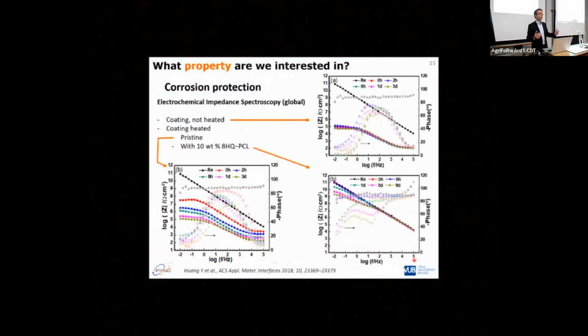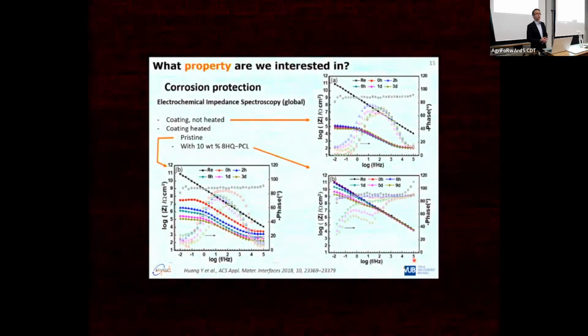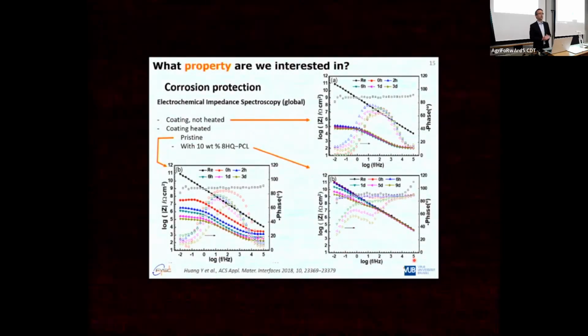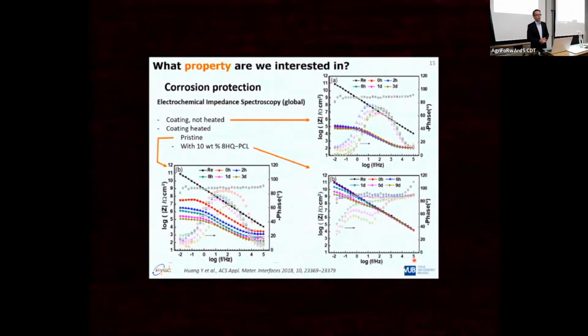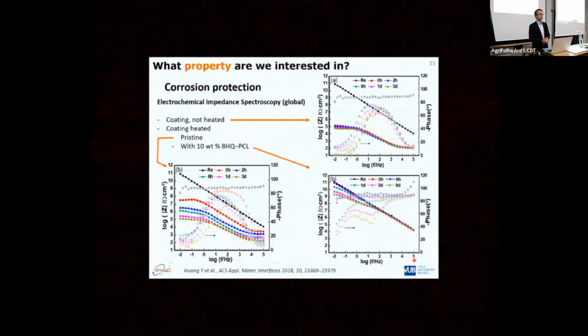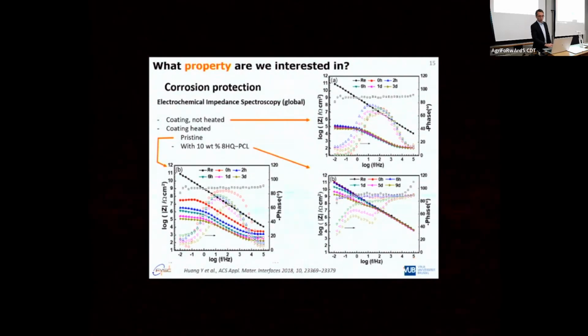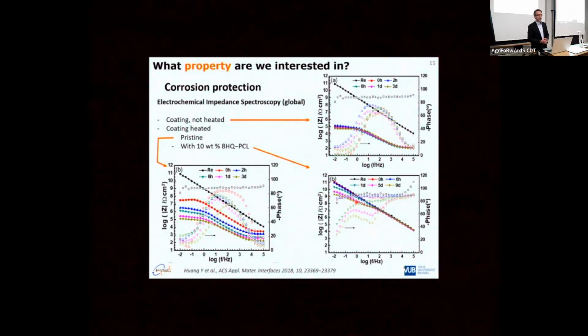But of course, you can also put multiple scratches on your surface and use electrochemical impedance spectroscopy, so the macroscopic variant, to then study the corrosion behavior and indeed also to observe in this case that you get a quite nice corrosion protection with this triple healing system.